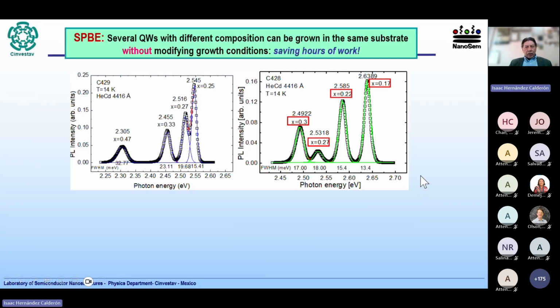So one of the advantages of this technique is that several quantum wells with different composition can be grown in the same substrate without modifying growth conditions. That is, we don't need to stop the growth, we don't need to modify the growth parameters as would usually be done by other methods, and we can grow in the same sample a large variety of quantum wells with different composition. For example, here I'm showing you two samples. Each one has 4 quantum wells with different composition, and we can even reach high cadmium content.